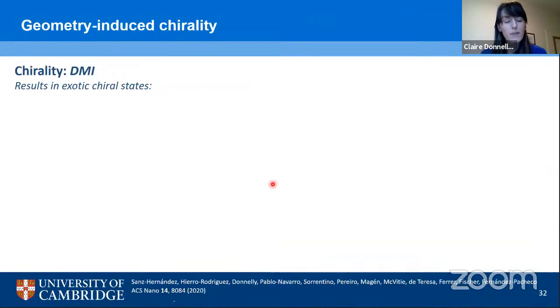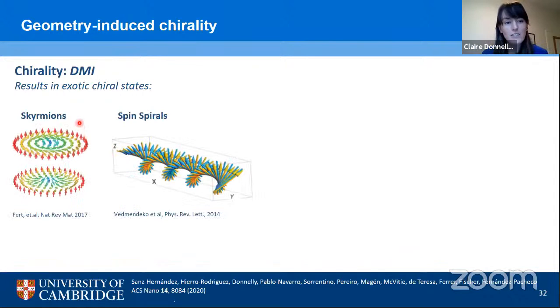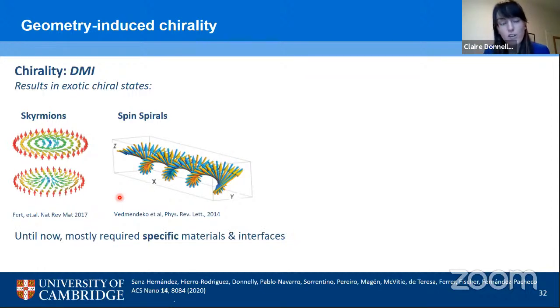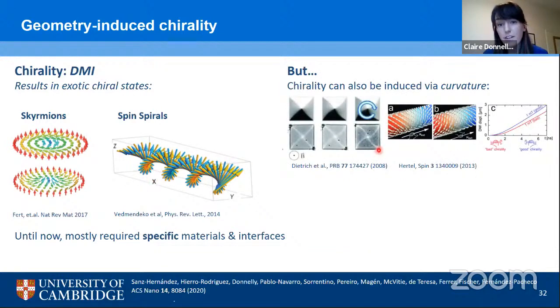magnetochirality. When we think about chirality and the Dzyaloshinskii-Moriya interaction, it is very well known for resulting in exotic magnetic configurations, such as skyrmions, which we have talked about already previously in this talk, but also structures such as spin spirals. However, to realise this chirality, up until now, the vast majority of experiments have required specific materials or high quality materials and interfaces. But chirality can also be introduced in other ways, for example, via curvature, where the curvature of a magnetic thin film can lead to, here we see, the twisting of a Landau pattern, or in three-dimensional nanowire structures or nanotube structures, we can have chiral domain wall motion.